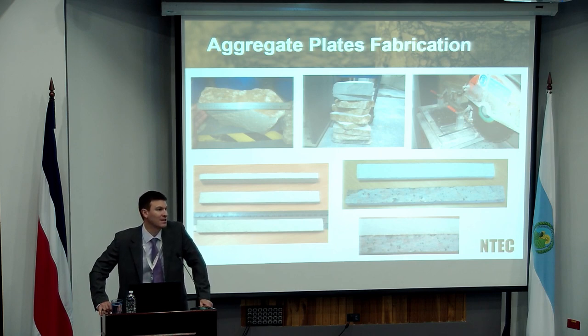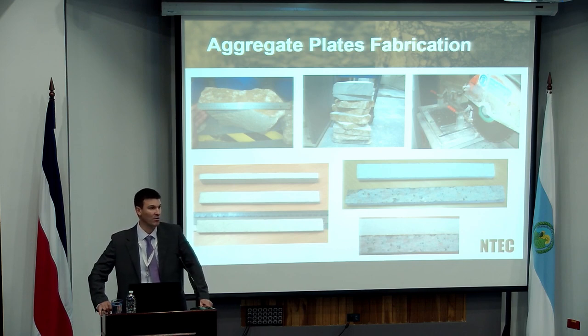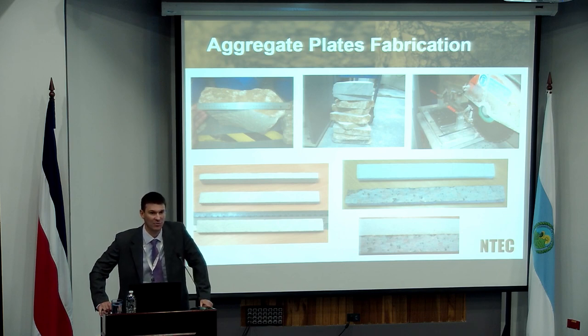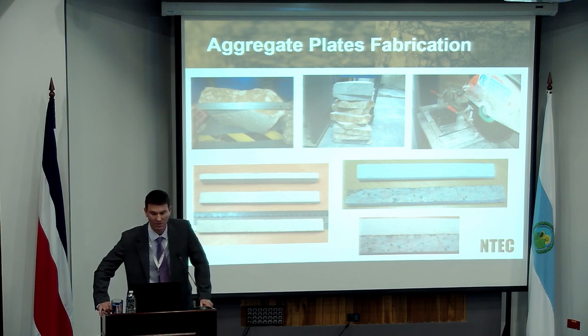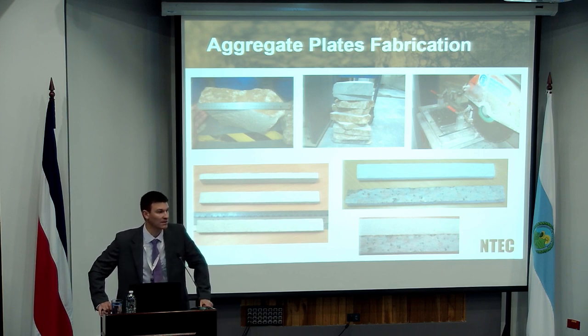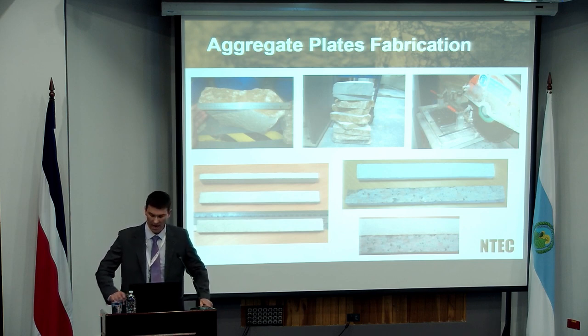The thickness does vary. The thickness will depend to a certain degree on how strong your aggregate particles are. So if you've got a very strong aggregate particle, you can probably cut it down to about 10 or 15 millimeters. If you had a material that was very susceptible to fracture, you obviously need to get a slightly thicker specimen. But effectively, the controlling geometry is that length of 200 millimeters and your width of 20 millimeters. And so the bottom two diagrams, one of those is an igneous rock, some form of granite, and the other one is a limestone. And you can see straight away we can produce a whole range of different types of aggregate substrates.